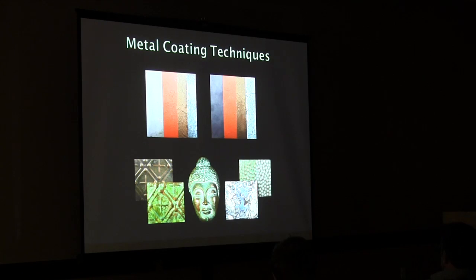And if you can get around 4 mils, because what happens is when the metal goes into the tank, it's molten, and the iron migrates up and bonds with the zinc. So you get incredible bonding, and you get something that's going to last up to 40 years if it's done right. Then you put a primer on. This is our bronze coating and a patina over the top, second layer. And you put it on while it's wet.